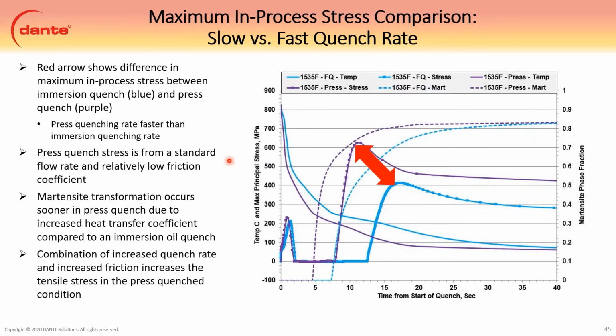This is just a quick plot showing stress from if you have a low friction press quench compared to an immersion quench or a free quench without constraints. So you can see the effect of the constraint and the friction. This also has to do with the slightly higher quench rate as well. So there's kind of two things going on here.